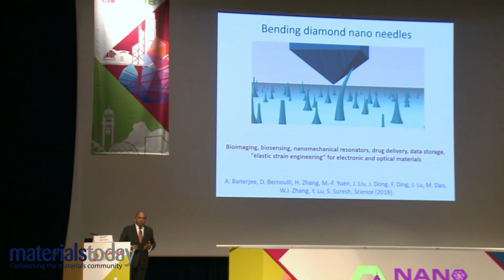We all know that diamond is the hardest material found in nature, and it's very difficult to deform diamond elastically beyond a small amount. Typically, when you go to a strain of as small as 0.15, 0.16%, diamond undergoes catastrophic fracture. It has high strength, of course. So is it possible, under nanoscale, to deform diamond to sufficiently large reversible elastic deformation that cannot happen under micro and macroscopic conditions? So that was the fundamental question.